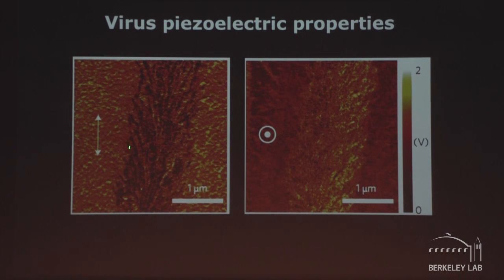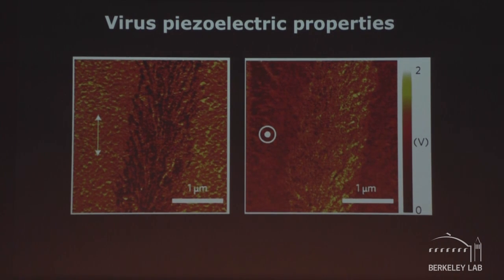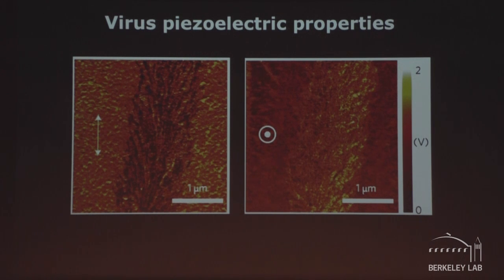When we scan through the virus surfaces, we begin to see white and dark stripe patterns, showing that these viruses are pushing the needle upward or downward. In the virus area, they push the needle in the out-of-plane direction. This confirmed that the viruses have piezoelectric properties.